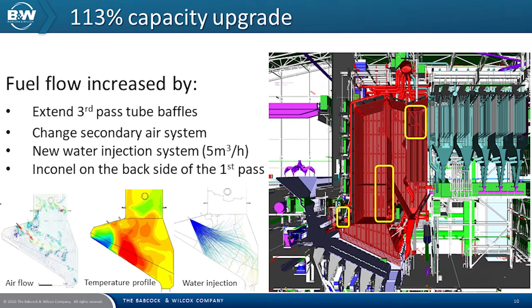So why did we use Inconel versus refractory? Inconel helps cool the area down. It helps to avoid slag formation and dripping. With the higher temperatures, there is a possibility of slag stalactites forming. So Inconel was welded on the back side of the first pass to avoid slag from dripping down onto the end of the grate. Inconel on the back of the first pass was also deemed to be the best value to the client.